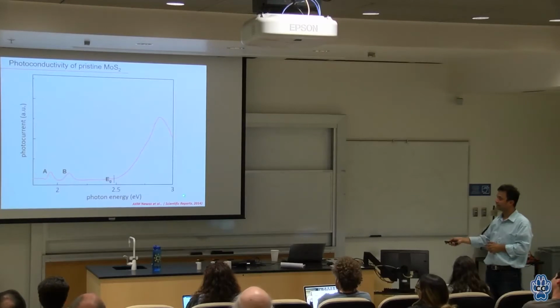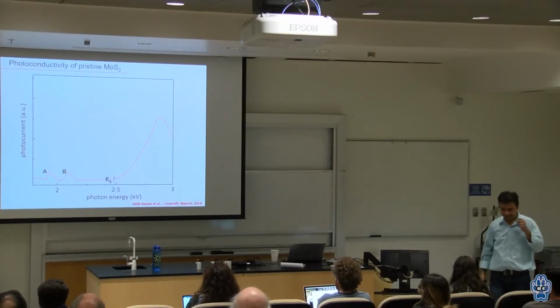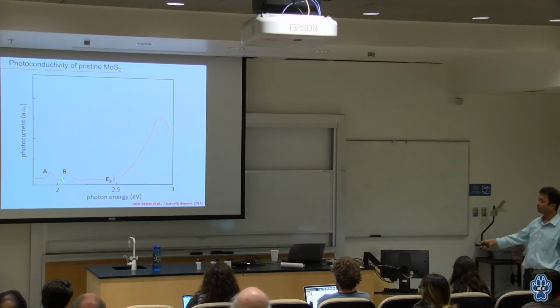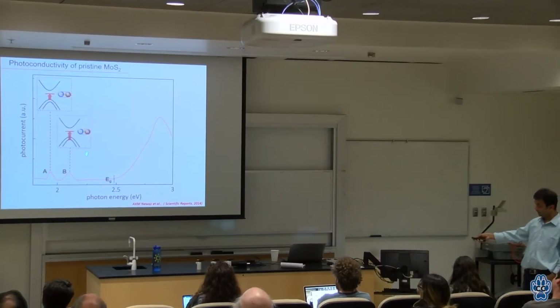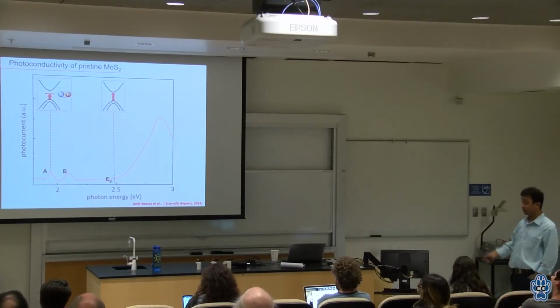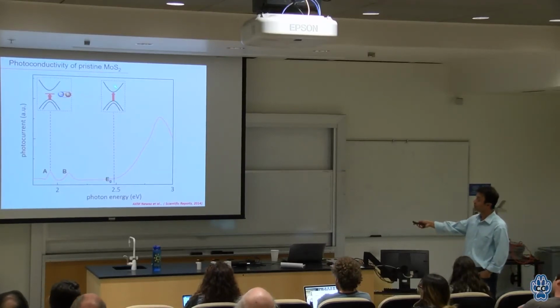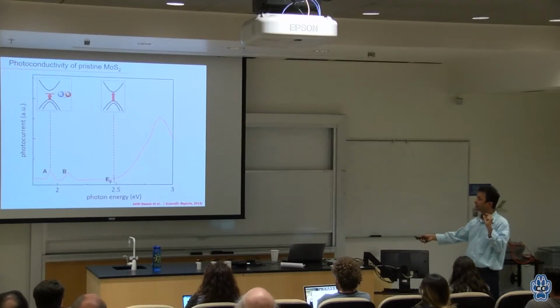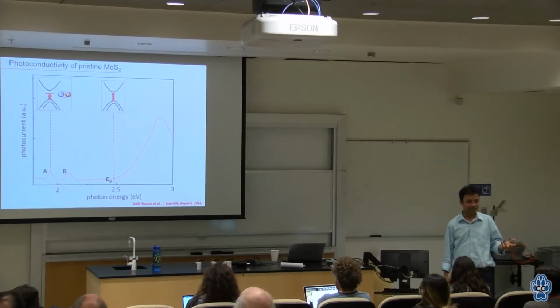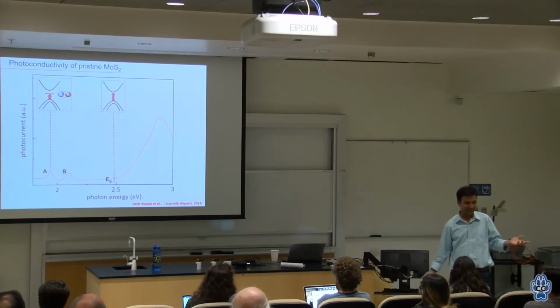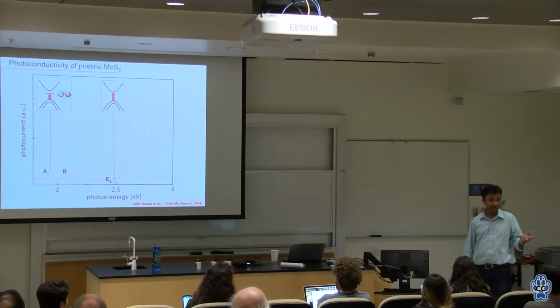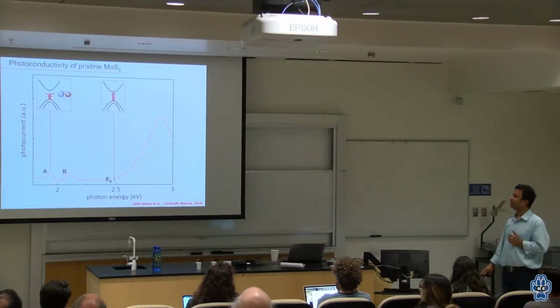This is the photocurrent as a function of color. You can see this is in eV, from UV all the way to red. All these peaks coming out are very similar to when you have a transition happening. You see big peaks when this transition happens, and this happens when you have this transition directly from here to there. If you subtract those two values, you can directly measure the binding energy of this exciton. You know the binding energy of hydrogen. What is that? 13.6 eV. This is around 500 meV, which is pretty large. So you can see all these effects even at room temperature. All right.